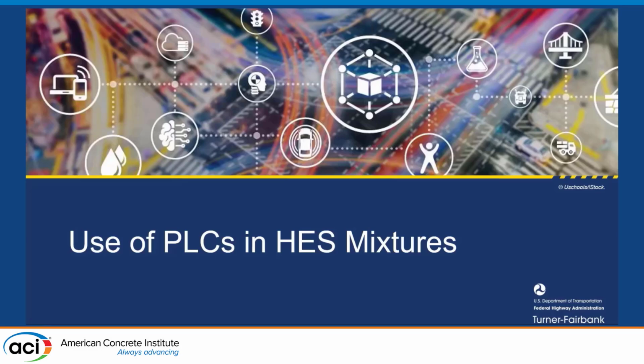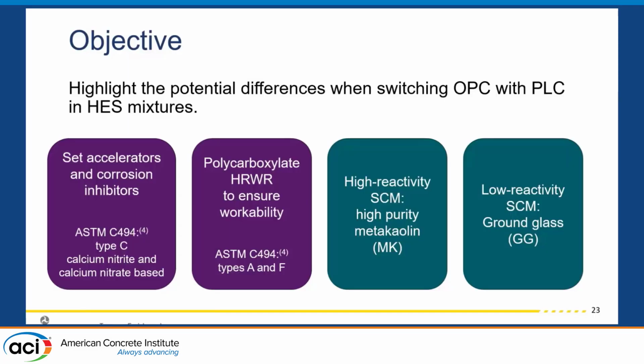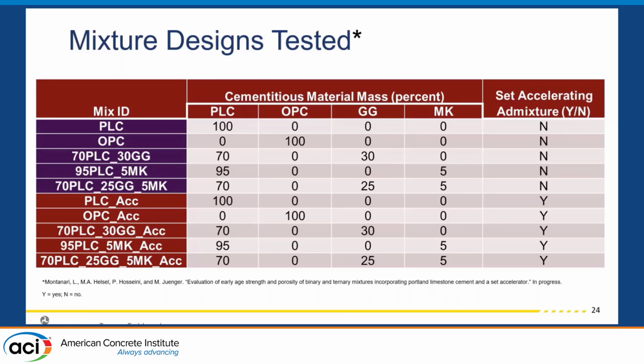So now switching gears into high early strength mixtures. Our objective here was to highlight the potential differences when switching from OPC to PLC and high early strength concretes. So we used set accelerators and corrosion inhibitors and polycarboxylate high range water reducer to ensure workability. And we used both high reactivity SCM and low reactivity SCM. We had a few different mix designs. I'm going to focus mostly on the OPC and the PLC. But what you need to see here is that a set of those had accelerating admixture, and then another set did not.